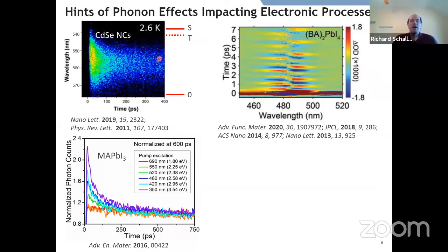And that said, in nanoparticles, it's understood that you form the lower energy triplet state quite rapidly at low temperature, and that this fast emission is due to the fact that you have phonons present, and the phonons can help you radiate efficiently from this triplet state, even though normally that would be a spin-forbidden process that is slow, which you're observing more here after the phonons have flown out of the system. And this is a picture that we first put forward in 2011, and many experiments that we do buttress this argument, and we think that it's in fact correct, but we can't directly see the phonons.